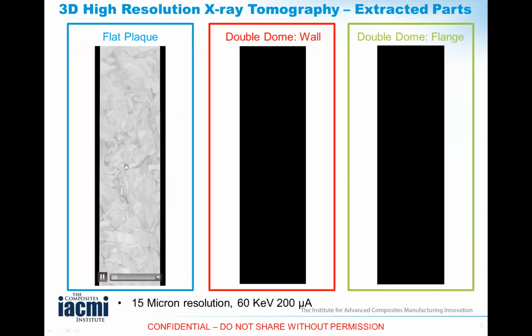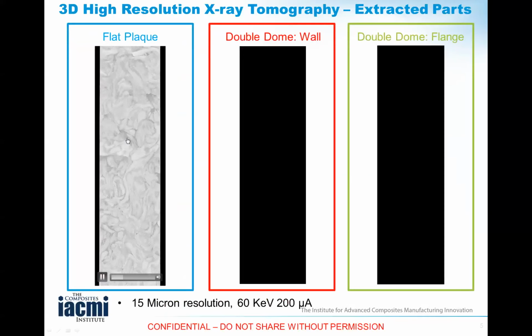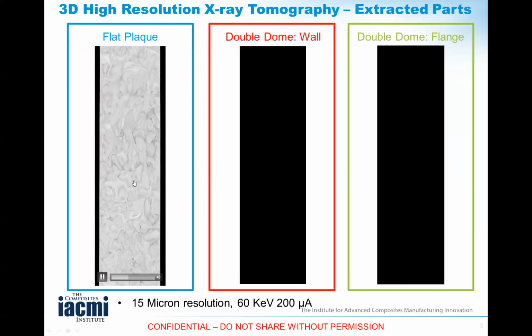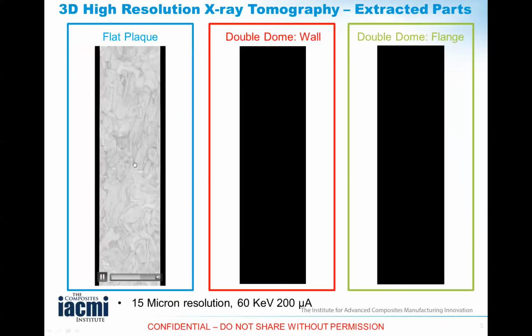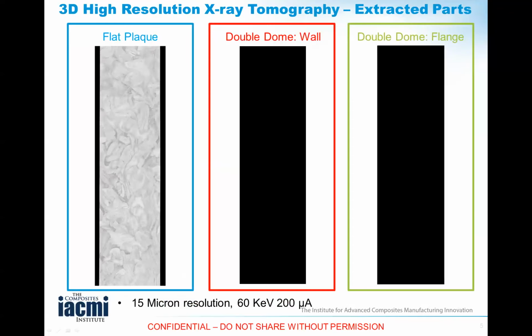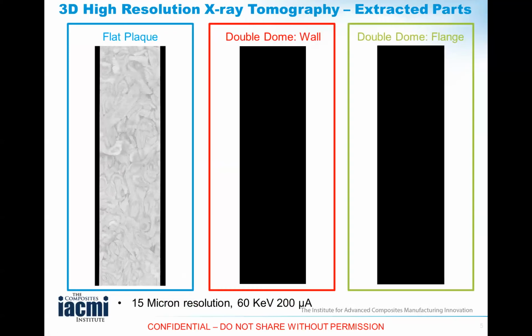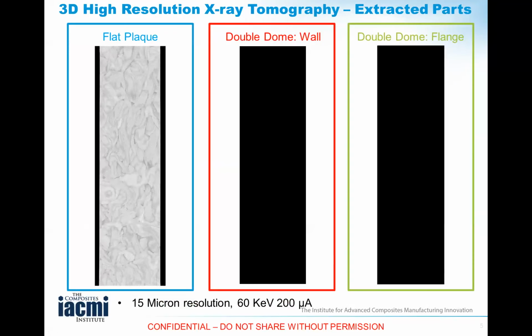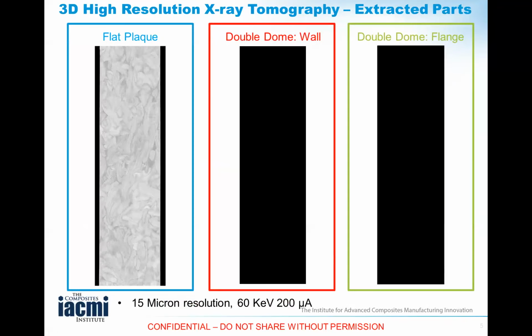So I'm going to run this video to show you that you see these platelets, they all start off rectangular, as Johnathan mentioned in his simulations, but after molding, there's a lot of three-dimensional curvature, both in plane and out of plane through the thickness. So one has to realistically capture this for predictive properties. If I play that again, and you have to take my word for it because you're seeing this for a very short time, the orientations in this flat plaque are more or less random. It's hard to believe when you look at it, but that's how it turns out to be.